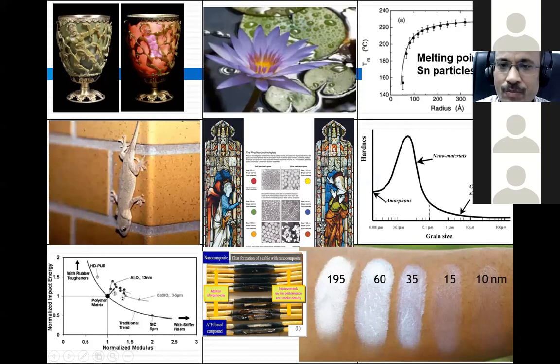This is very important. On the right side, you see how the hardness or yield of the materials increases when you reduce the grain size. You can see when the grain size is reduced from hundreds of micrometers to less than 1 micrometer, or close to 30 to 40 nanometer, the hardness is highest when the grain size is about 20 to 30 nanometer. Below that, again, hardness decreases, but the resultant hardness is always higher than the hardness of the microcrystalline material. Okay, this is very important.